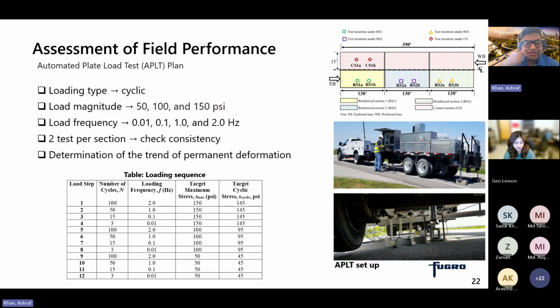And if you look at the table, you can see the loading sequences. So it is using 50, 100, and 150 psi of load with different frequencies. The purpose of doing this test: one is, in each section we had two tests, so we can check the consistency or repeatability of the test. And the purpose was to capture the elastic and plastic deformation so that we can prepare the rutting model from here.